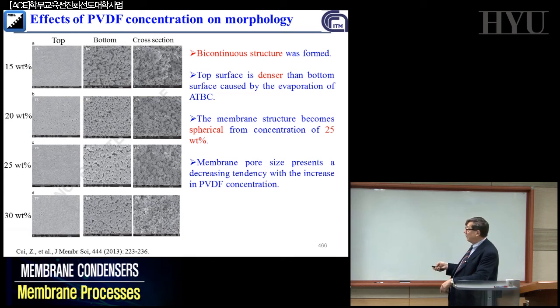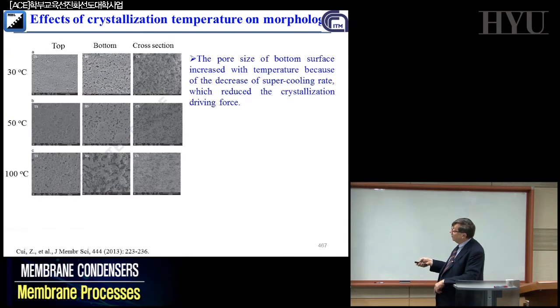For example, the membrane pore size presents a decreasing tendency with the increase in PVDF concentration, which is related to the kind of structure that you are realizing with concentration higher than 25. And these are quite interesting differences. The pore size of the bottom surface increases with temperature because of the decrease of supercooling rate, which reduces crystallization driving force. So these parameters are 100% related to the kind of solvent you are using, and they are related to the polymer you are using, obviously, but not only to the polymer, but in phase inversion to the kind of solvent. Change the solvent, all the recipe will be different.